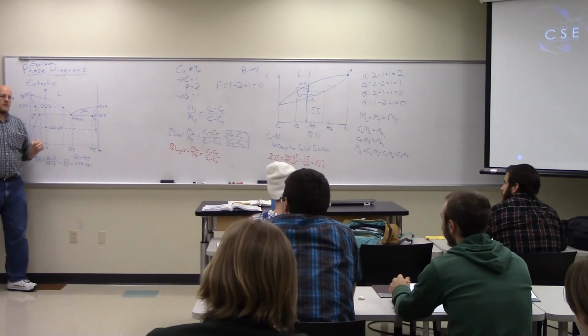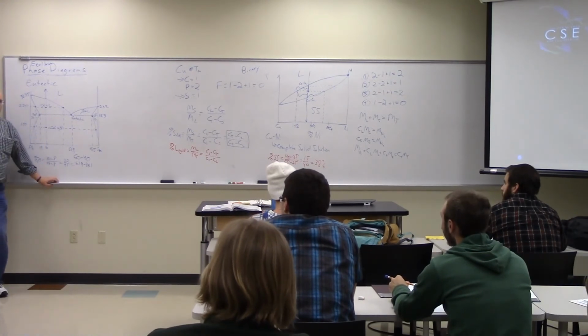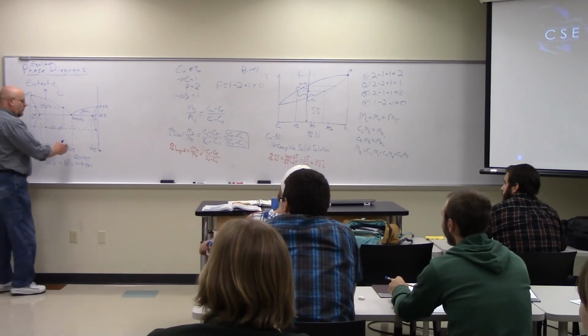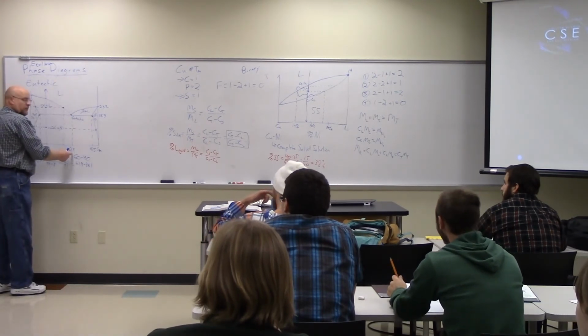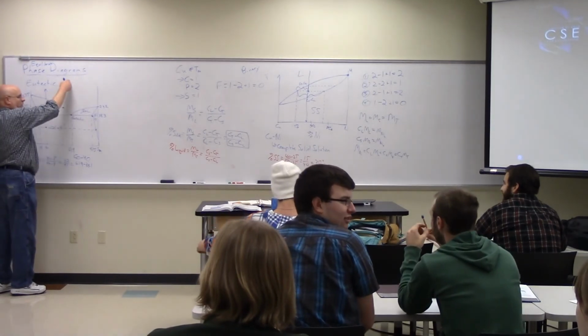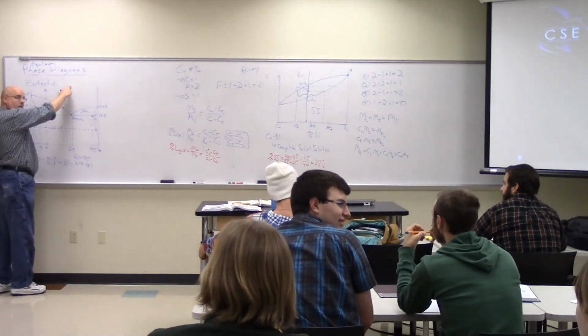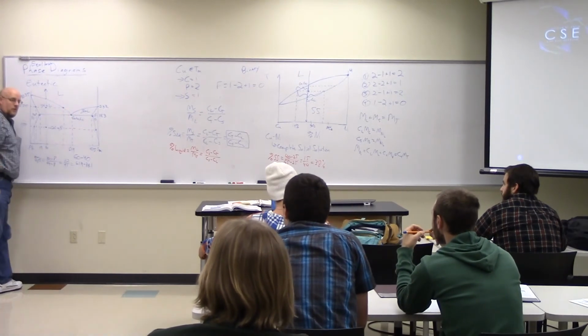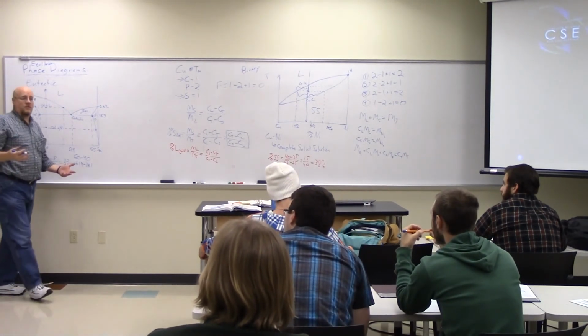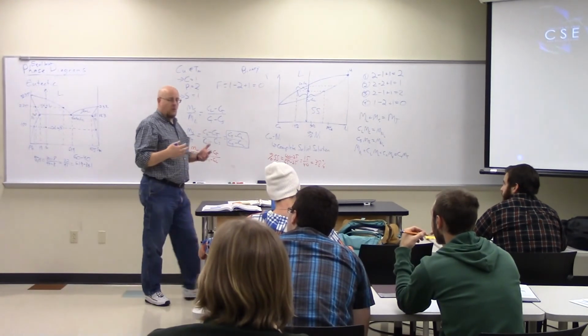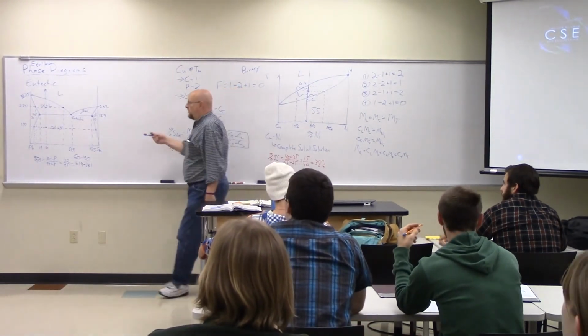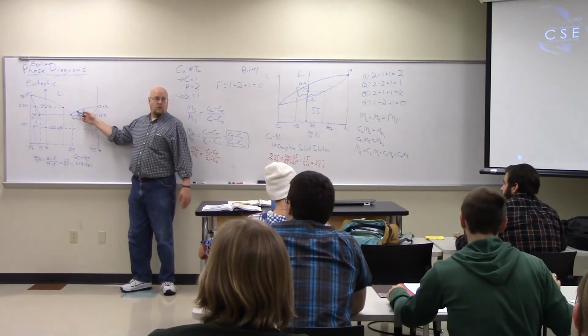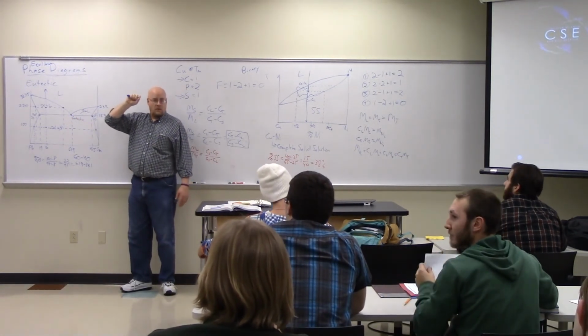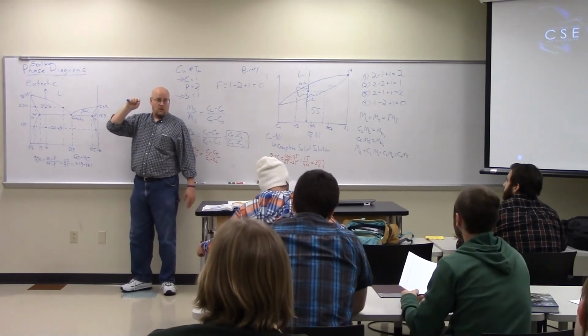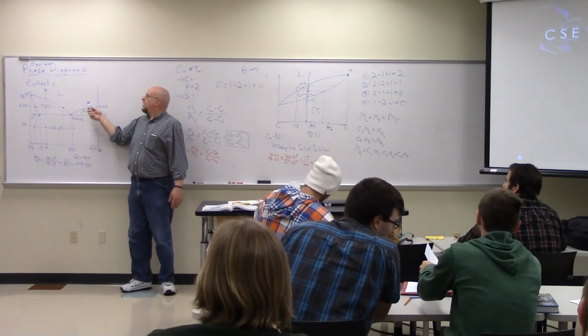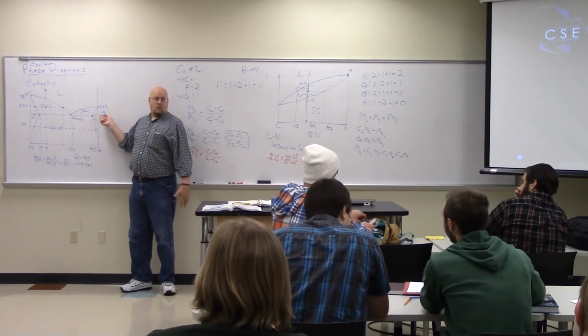So what happens if somebody comes in, puts the soldering iron on 700 and starts to go at it? Well, all you're doing is just moving on this line, because the solder's fixed to that composition. You set the solder to 700, you're wasting time, because you melt the thing, you gotta let it cool down that much further. That's why lead tin solder is advantageous, and using lead-free solder is more of a challenge, because you have to find another composition that allows you to get a pure transition from liquid to solid at one point, so it doesn't get slushy.